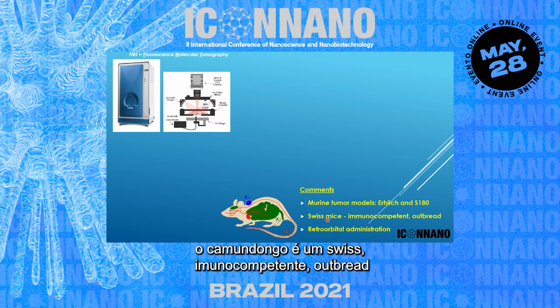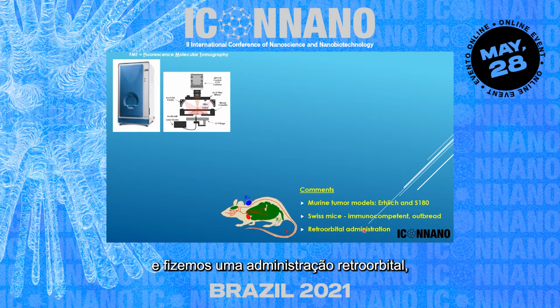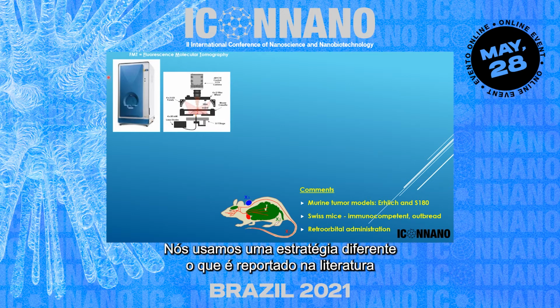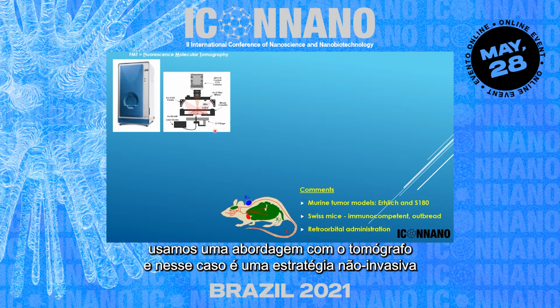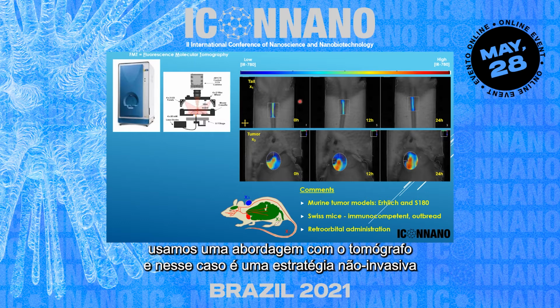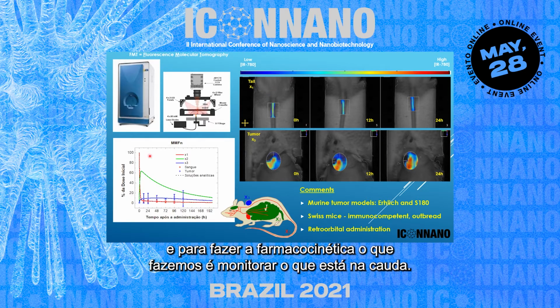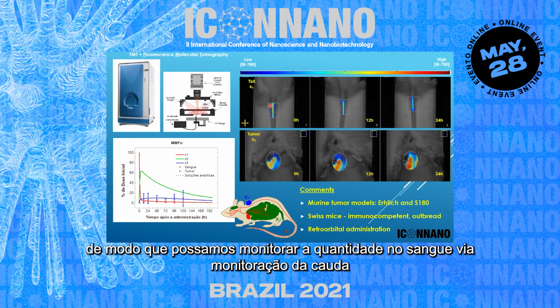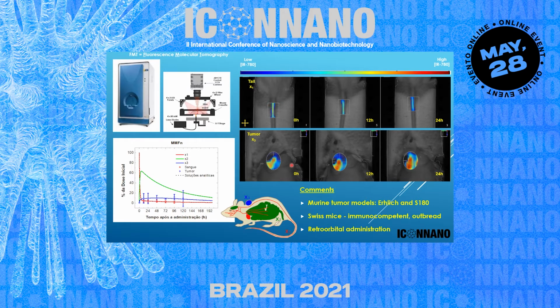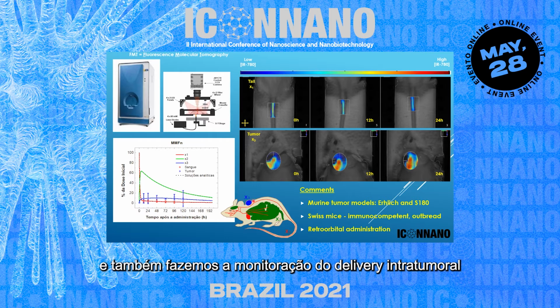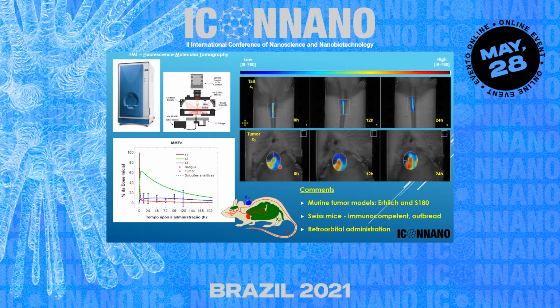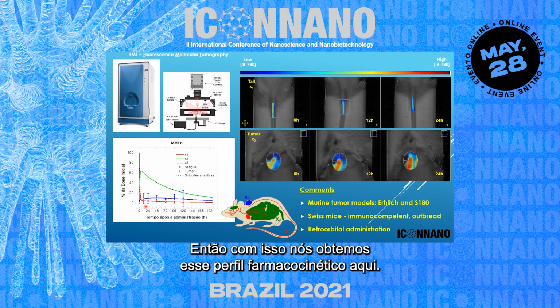So to perform our pharmacokinetic studies, we used Ehrlich and S180 murine tumor models. The mice are Swiss mice, which are an immunocompetent outbred strain, and we perform a retro-orbital administration. We are using a different strategy from the literature. It is a fluorescence molecular tomography approach. In this case, it is a non-invasive strategy. And to do the pharmacokinetics, we monitor what is in the tail. That's why we do retro-orbital administration, so we can monitor the amount of this nanocarrier in the blood by monitoring the amount in the tail. And we monitor the intratumoral delivery by also putting a ROI in the tumor region. So with that, we get this pharmacokinetic profile here.